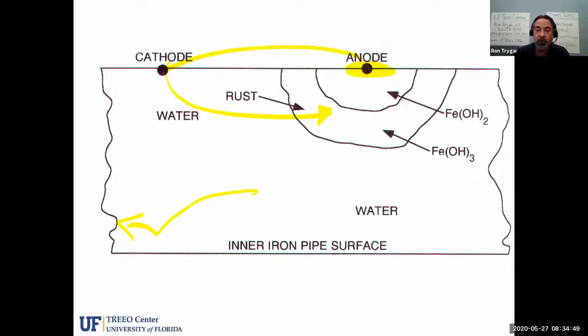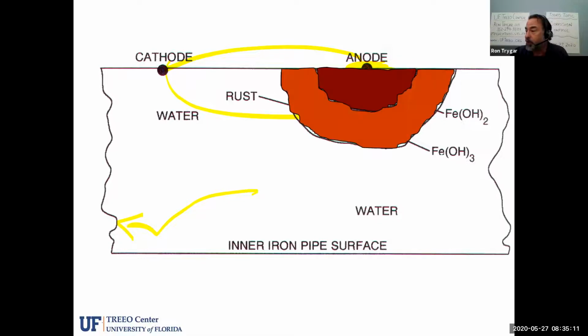So the more exposed metal there is to the oxygen, the more it starts to rust. The anode is where the tubercle forms. The anode is also usually where the leak happens, because that's where the pipe wall thickness is getting thinner and thinner. So again, the tubercle starts to form. Now, if the water velocity is very slow and this is occurring, then it could form a multi-layered tubercle, which we discussed a little bit earlier.